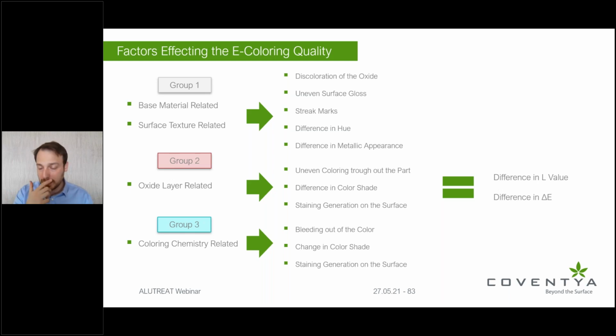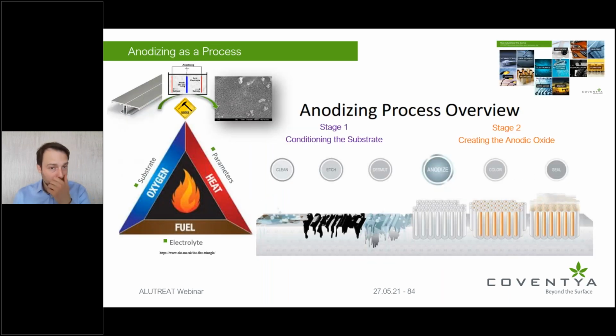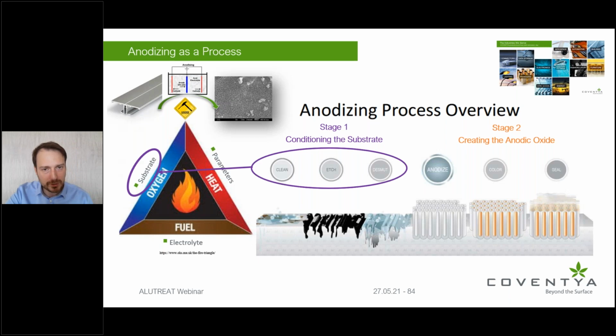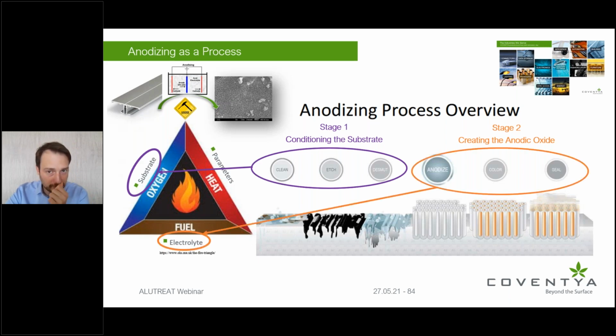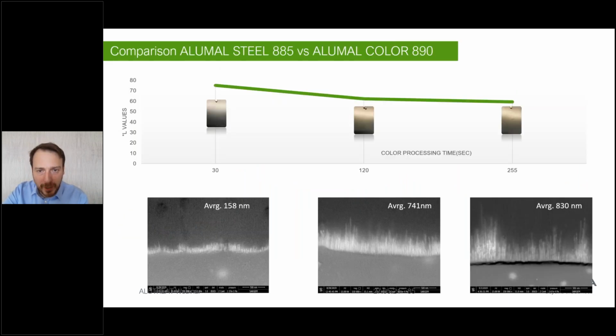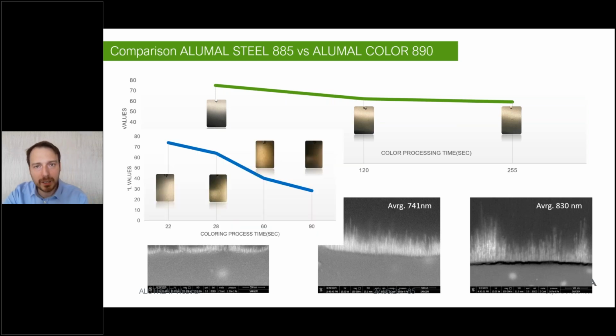Finally, you also need to understand what type of oxide has been applied so that you can decide what type of color you should choose and apply as a process. Therefore, it is paramount to use not only anodizing or pre-treatment, but a combination of these in order to adjust your substrate and then create the right oxide film on which or in which you can precipitate your coloring agents.